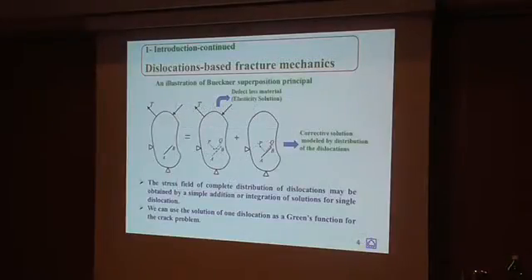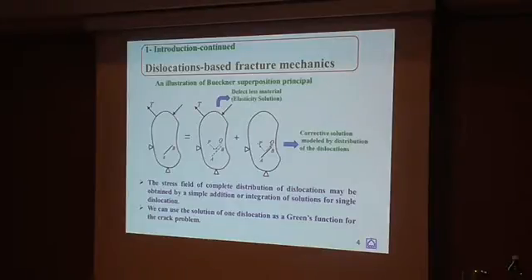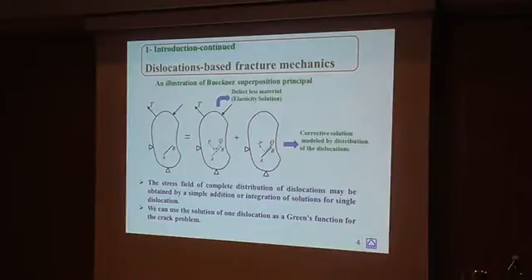We use imperfect bonding between the magneto-electro-elastic layer and the orthotropic substrate. With the use of the distributed dislocation technique, we employ and apply this method to solve the problem. The main problem with the crack and external loads is divided into two sub-problems; the first is the elasticity problem in defectless material, where we find the traction on the crack location.